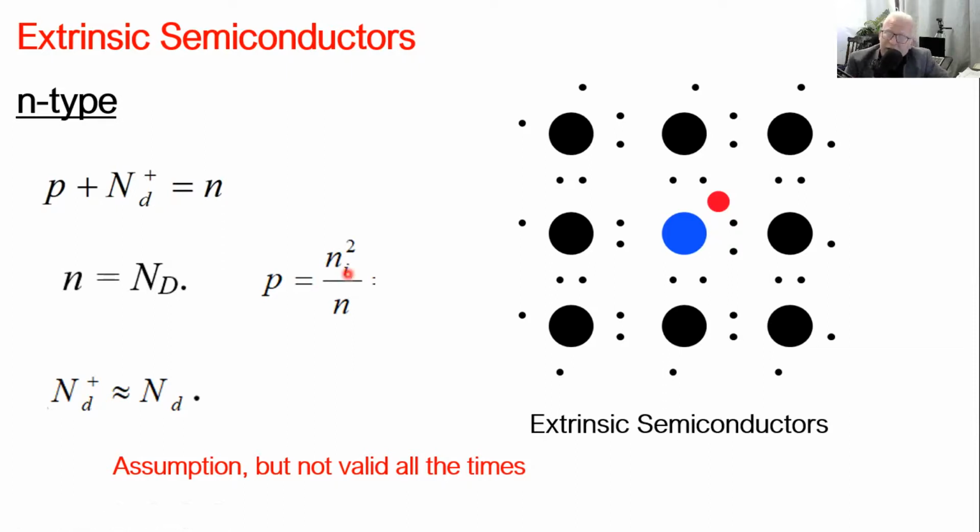So for an n-type, first you have doping with an impurity material. This impurity material relates to the 5th group; it has 5 electrons in its outermost energy level. After replacing your silicon atom with the impurity atom, which is a 5th group atom, one additional electron appears. This electron is not involved in any bond, so it's partially free.